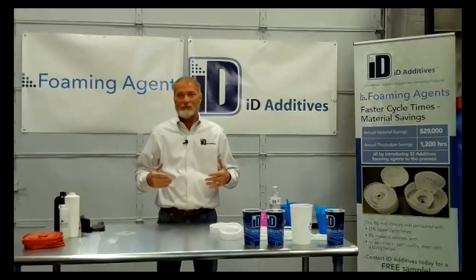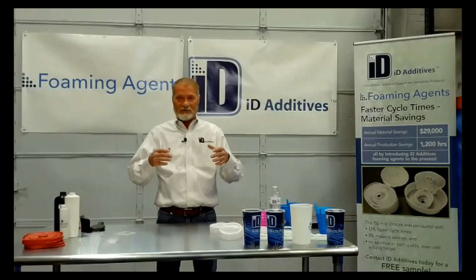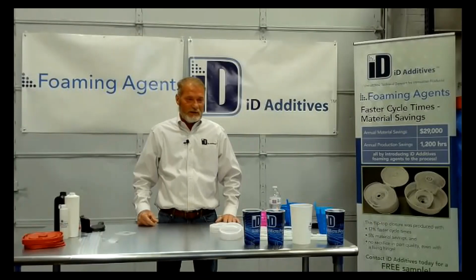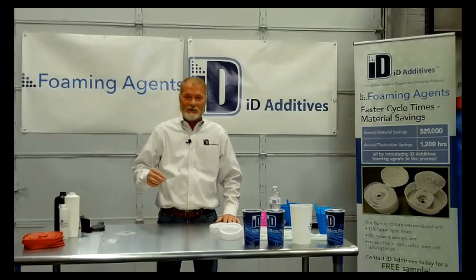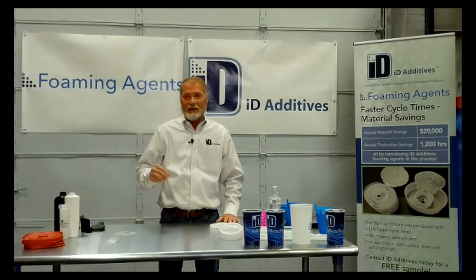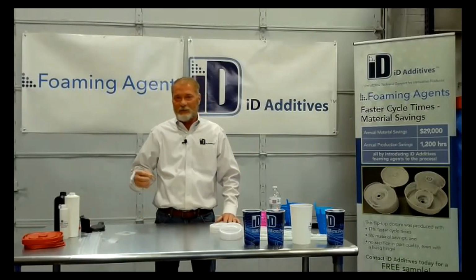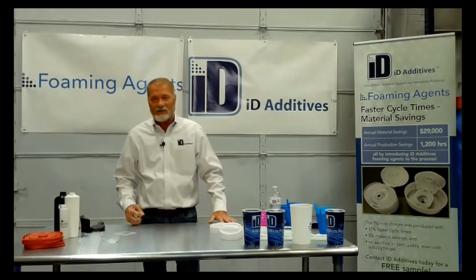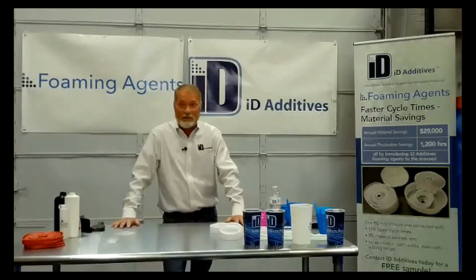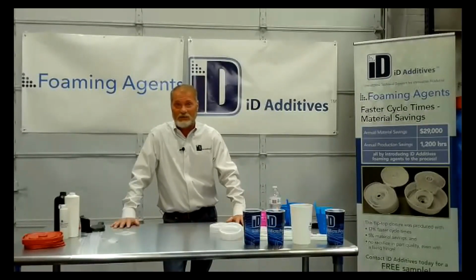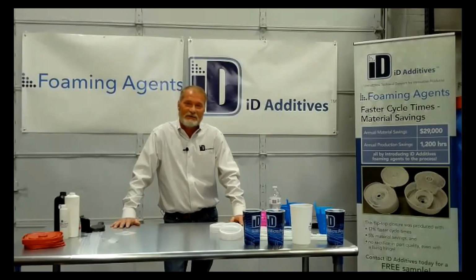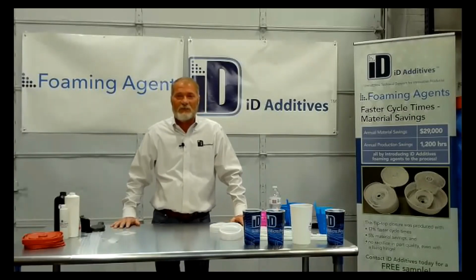Otherwise, they try to come out too fast, and they'll start bubbling up and expanding in the thicker sections. So it's really tough to meter a 0.2% foam in a part with an auger feeder. But if we add it to a 2% color, now you're dispersing that 0.25% foam or 0.2% foam at 2% let down in a color. So you get complete dispersion on lower percentages. And it's a cost savings too, because you're paying for two different products. We can give you one.